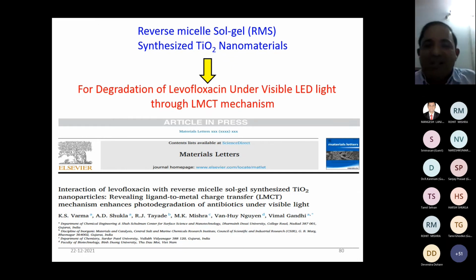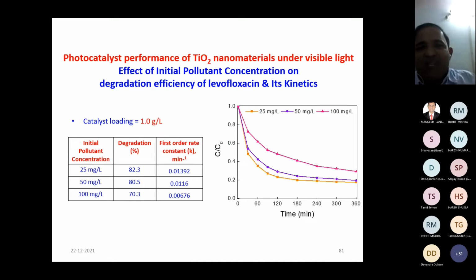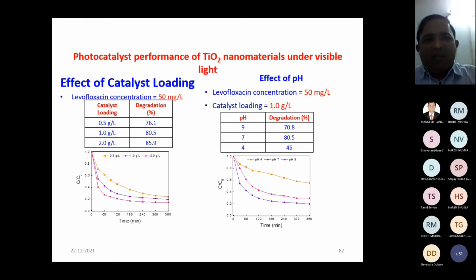And we reported it; just last month it was accepted, and this is a very interesting phenomenon that we found in the case of levofloxacin. So here the catalyst loading is 1 gram per liter, and as the initial pollutant concentration is increased, degradation is slightly reduced, but yes, we are getting this degradation under visible light. Once again I repeat, it is bare titania, it is not doped titania, and still we are getting visible light activity.